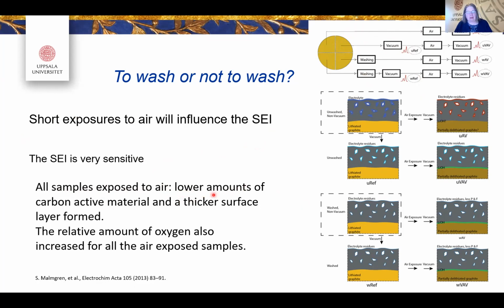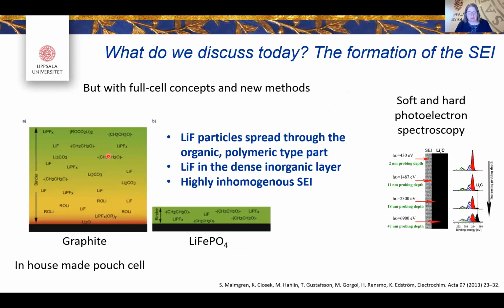And you get lower amounts of carbon active material, thicker surface layers form, a lot more oxygen also, and that increased. And if you have lithiated graphite, it actually delithiated during this short time, and you could find then that you had extra lithium oxygen, lithium hydroxide layers on top of the graphite surface.